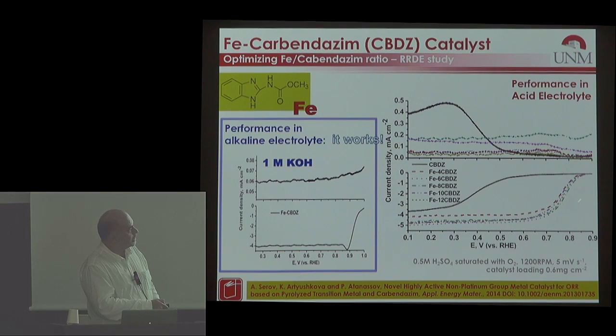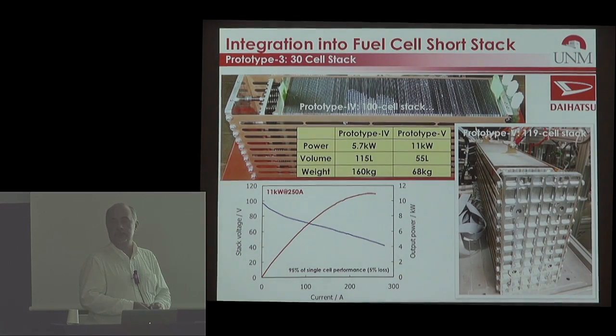So the catalyst increases its activity and reduces the amount of hydrogen peroxide released from the catalyst when you increase the amount of nitrogen in it. And you incorporate the iron in that material better, resulting in homogeneous distribution. What you can also see is that in base, all these catalysts perform fantastically well. So the only problem is to find a company that really likes to make fuel cells that are alkaline.